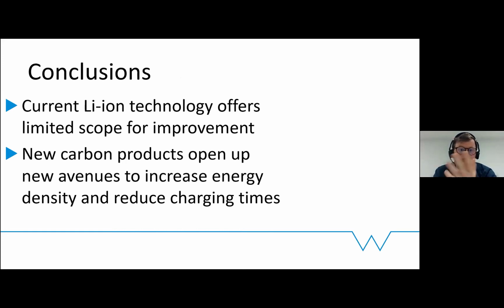The current lithium-ion technology, with the new carbons that are being generated as additives, at sub 1 weight percent, really are showing a lot of advantages in terms of energy densities, reduced charging times, stability of the coating, and stability of the overall system.